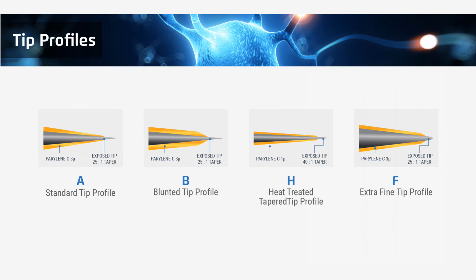The heat-treated tapered tip profile is for those that intend to insert their electrodes through tough tissue, such as dura or other tough membranes. How this works is that, for those trying to insert a standard electrode through a tough membrane, it can end up pushing the soft insulation layer back, changing the impedance of the electrode. Often, this becomes more and more a problem with repeated insertions. The heat treatment actually hardens and bakes the insulation, causing it to become more resilient and stick more to the electrode surface. This allows it to hold up to multiple insertions without being pushed back from the electrode.